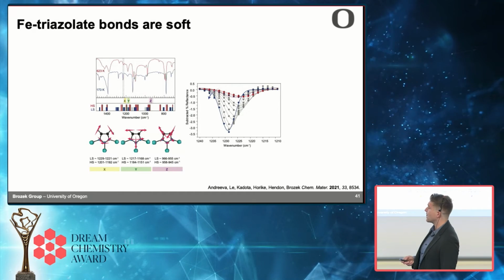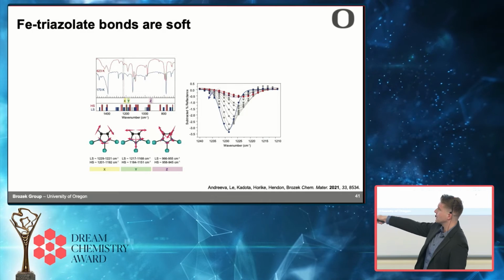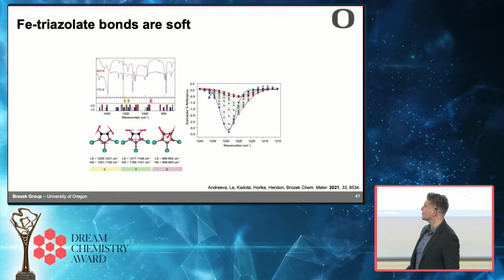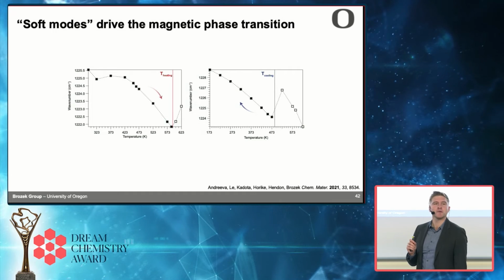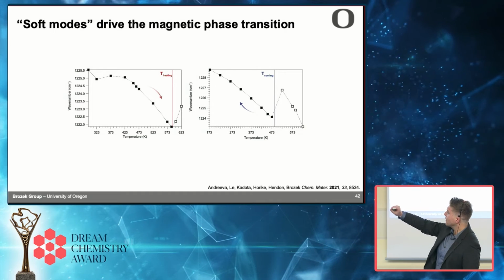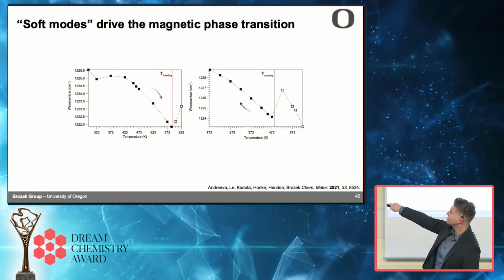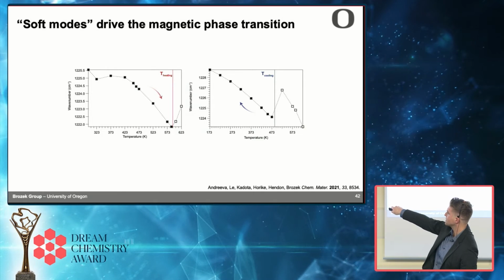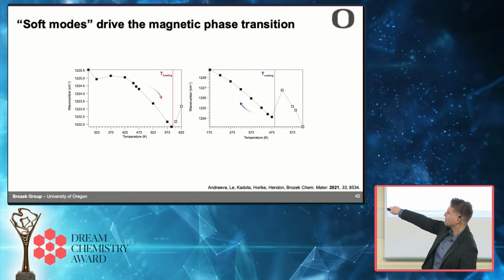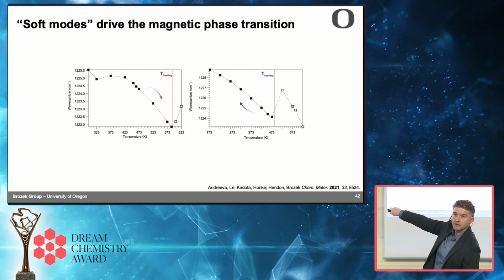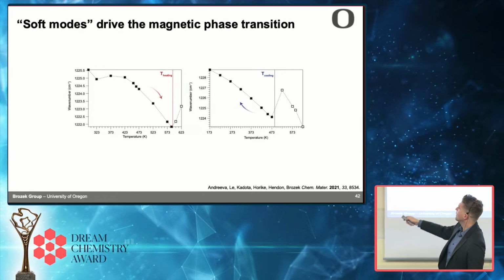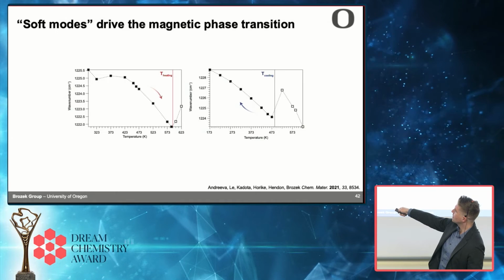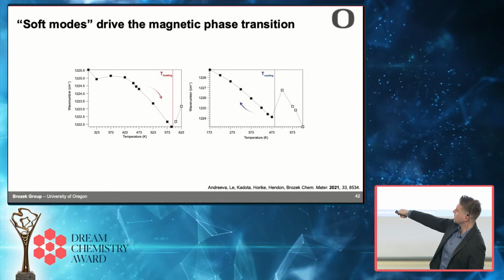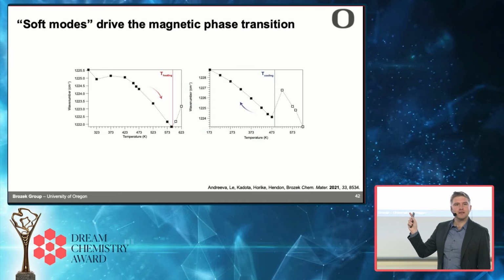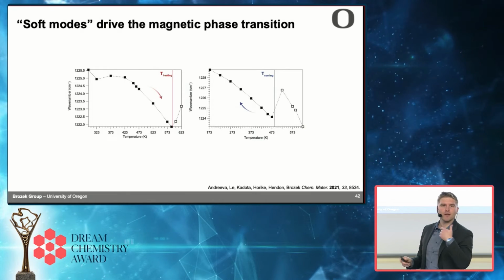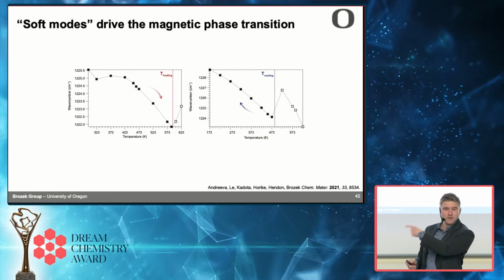So we measure its IR spectrum as a function of temperature. Here's that triazolate stretch. It redshifts and blueshifts reversibly as you heat and cool the material. But something really special happens in this case. As you plot the frequency of that triazolate stretch and you heat it, it redshifts, just like we saw for the previous material. But right at the reported spin crossover temperature, you see that inversion like I showed you for strontium titanate. You can cool it, it'll blueshift, but then right at the spin crossover temperature, you get that inversion. And what this says is that the iron triazolate stretch, this dynamic stretch, is acting as a soft mode, because this is the hallmark evidence of a soft mode.